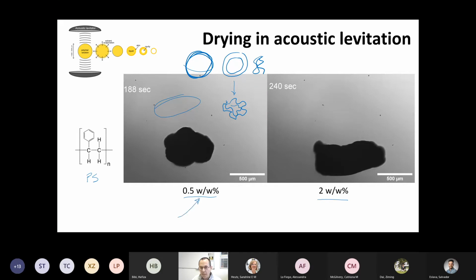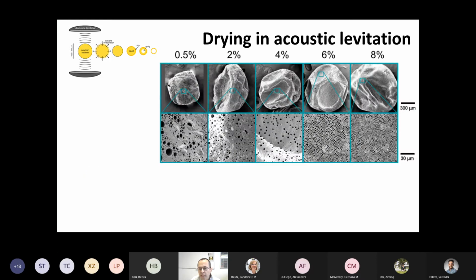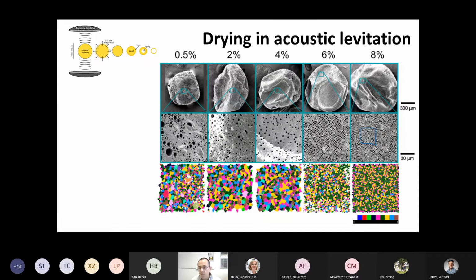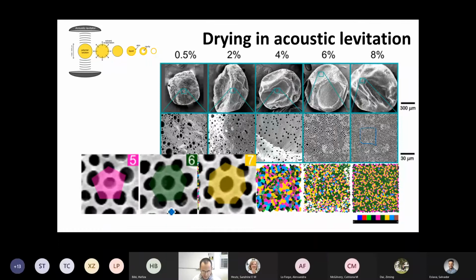But not quite linearly, of course, because as we realize, these particles are anything but compact. If you inspect them now with the SEM on the surfaces, you realize that they are actually fascinating. And so, for example, you can see that very nicely. We can excite some kind of patterns that are extremely regular at the surface beyond this kind of overall sultana shape, sort of envelope of the particle. These you can analyze with standard methods. This is called a Voronoi analysis that looks for the number of nearest neighbors and concludes here that these types of particles have predominantly 6 whenever you excite these kind of regular shaped arrays.